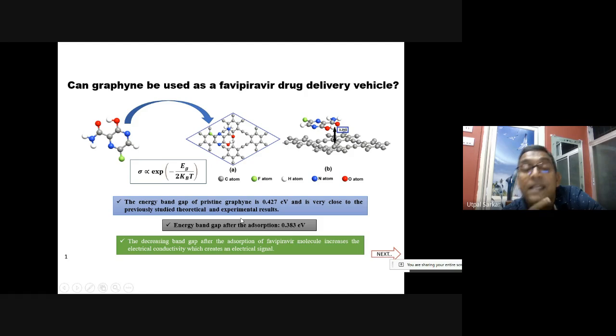Now, another thing is whether this graphyne can be used in bioscience as a drug delivery vehicle. So what we have done here is that we have taken a favipiravir molecule and studied its interactions with the graphyne. The energy gap of the pristine graphyne using DFT calculations is 0.427 electron volt, which is very close to the previous theoretical results that we have found.